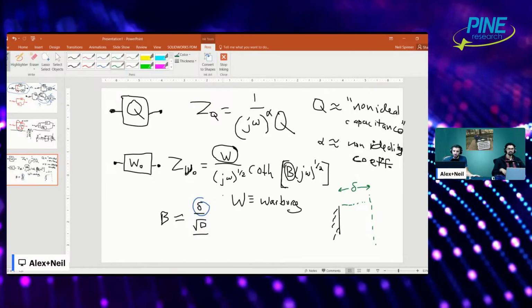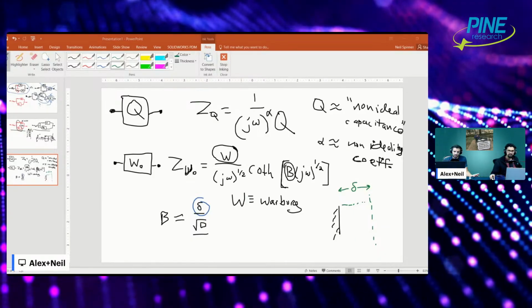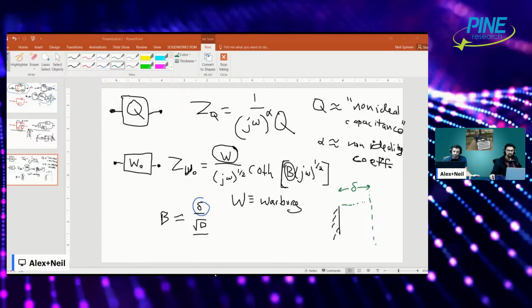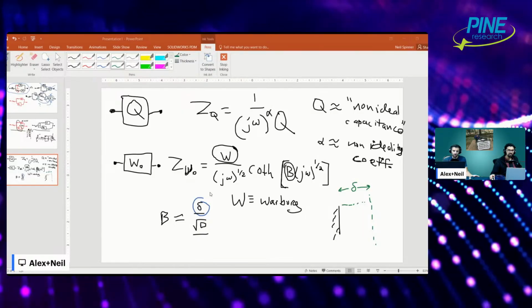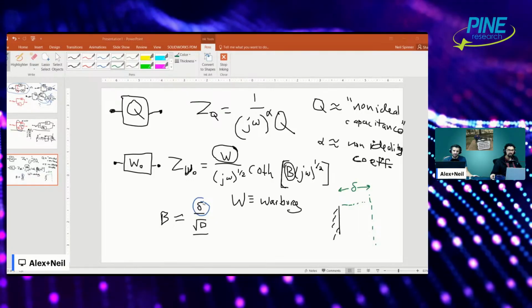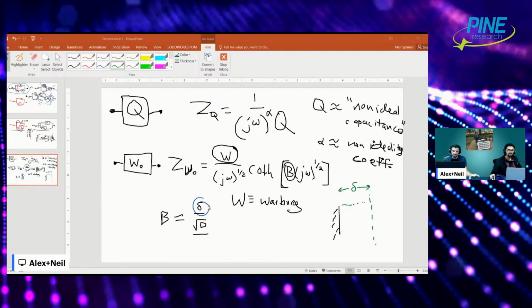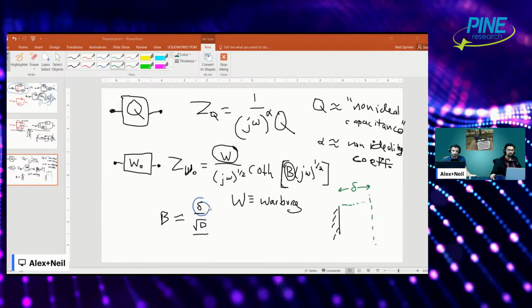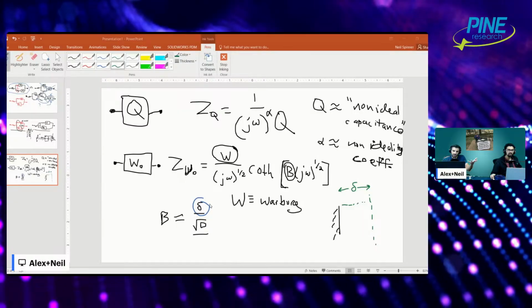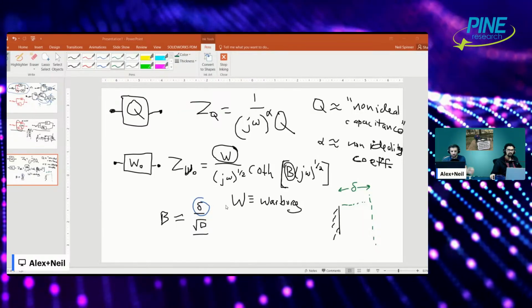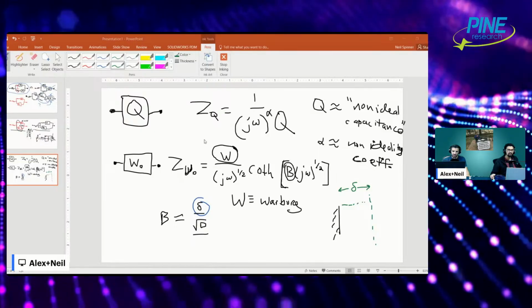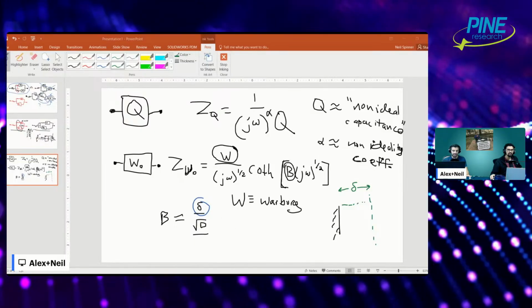And so if you're fitting with a Warburg open, I guess to the point of your question, if I'm understanding it properly, is like, well, would you report all these constants? Well, probably, because if you're getting a Warburg open fit, you have a B, and reporting the B value gives you some indication of the thickness of the diffusion layer. And if you're fitting a finite Warburg, you're probably interested in the diffusion layer thickness, because that's why you're fitting the Warburg open. Maybe. So it's reasonable that you would report those values, but those are the kind of the significance, I guess you'd say, of the parameters you get out of those two fitted elements in impedance data. So there you go. Okay.